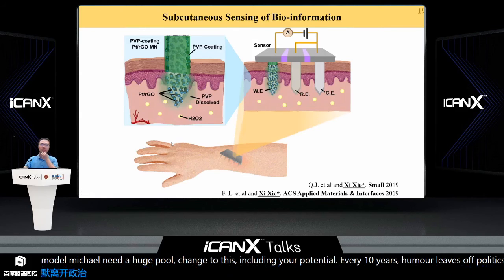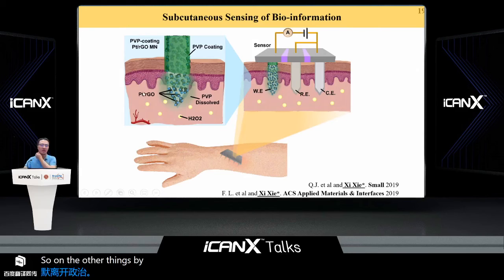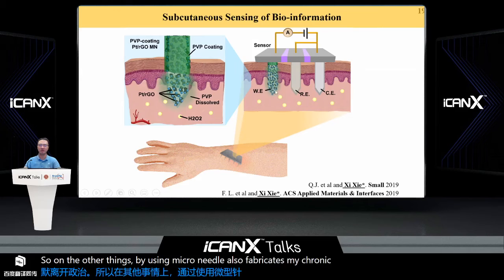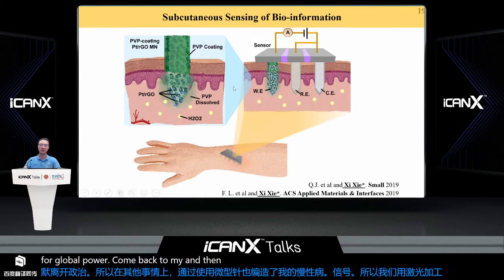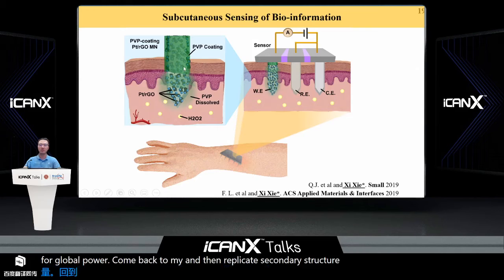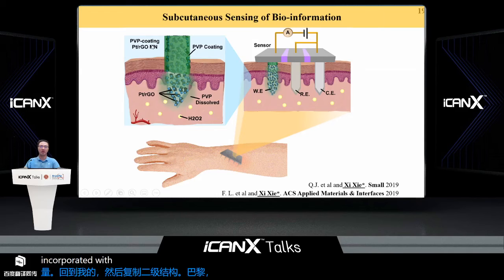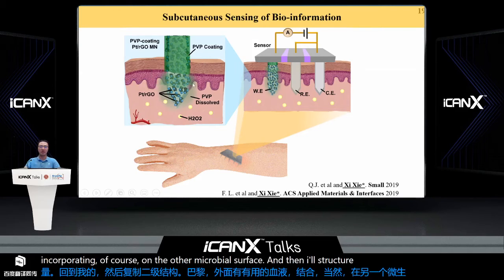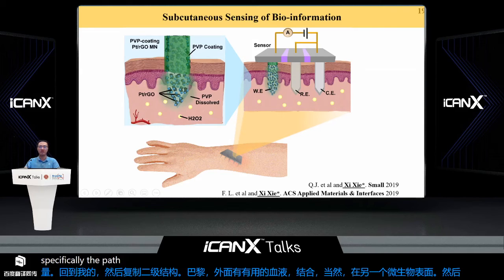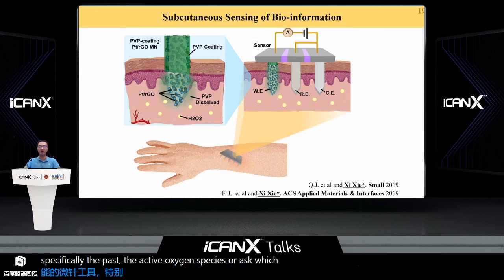On the other hand, by using conductive microneedles, we can also fabricate the microneedle into a biosensor to detect biological signals underneath the skin. So here we use laser machining to prepare conductive microneedles, and then fabricate a secondary nanostructure, that is, hybrid reduced graphene oxide incorporated with platinum nanoparticles, on the microneedle surface. The nanostructure could enable the microneedle to specifically detect reactive oxygen species, ROS, which is generally associated with inflammation.